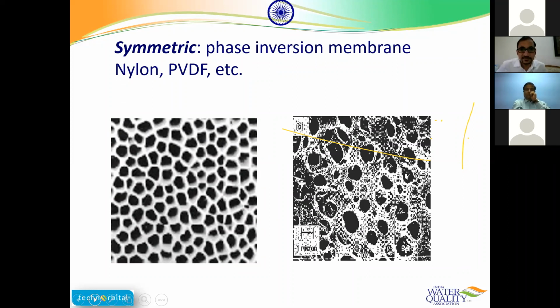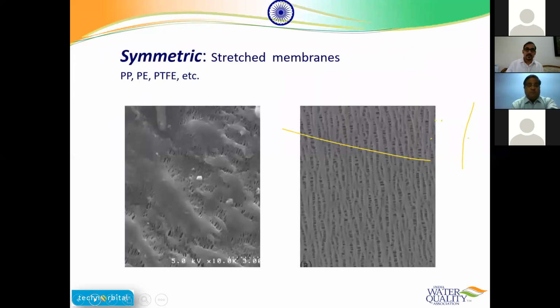This is a phase inversion membrane, phase inversion process. Again, very nicely organized pores and all that. Again, symmetric, but a different process here. These were sheets which were stretched in a certain manner to get this kind of porosity. Very well organized, aligned. So these are PP, polyethylene, polypropylene, or PTFE membranes.